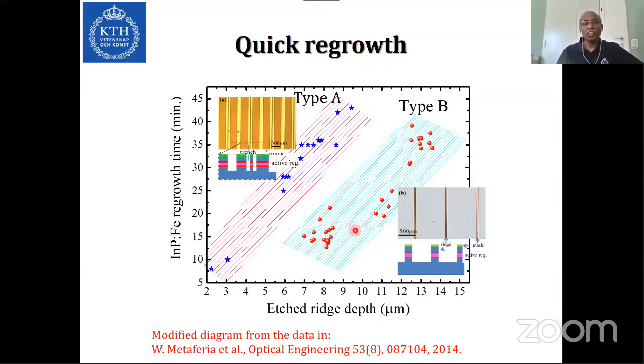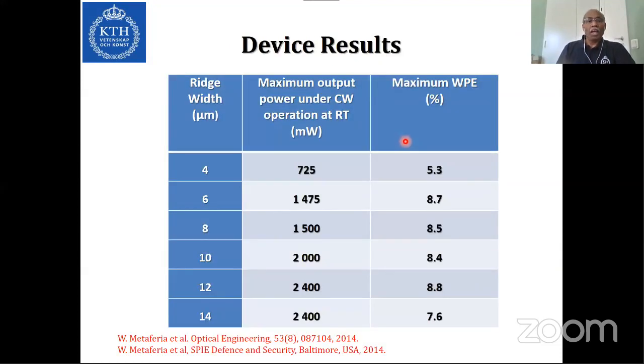Depending upon the etched ridge depth, you have the regrowth time. And you see even to regrow 14 micrometer deep trenches, you need only 35 to 40 minutes. So this is a dream for MOVPE, which cannot be easily done. And these are some of the results of the ridge lasers. We could go up to a maximum output power of about 2.4 watts, and the wall plug efficiency around 8. So these are all really very, very good results.